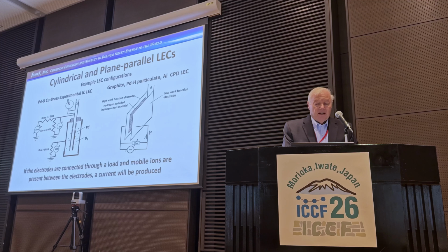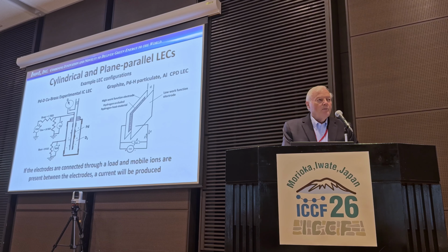It's a simple looking device. You see on the left is just a pipe that has a pipe inside it. And the one inside has palladium co-deposited with a hydrogen included. The outside one is just a brass pipe. And initially we started by applying a current because we thought if we can ionize through gas, then we can go to higher temperatures without having to worry about higher temperatures with oxygen and hydrogen evolving.